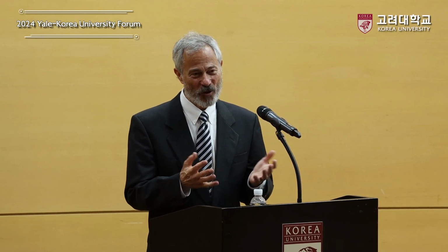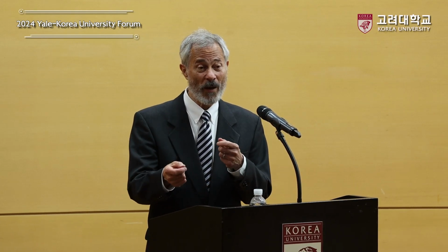So I do think iridium is not necessarily too scarce to be able to do this work. But we're very much interested in trying to find more earth-abundant elements, particularly first-row elements. The real challenge, and this is a challenge facing the entire field, is that the bond energies of ligands to first-row elements are much weaker. And so they rearrange much more readily. And we have not been successful to find a catalyst that's very stable based on a first-row system. And that's going to be a challenge to come up with design principles and design approaches that will give stability. But we're very much interested in other metals, and maybe even a bimetallic system with iridium with another metal might also be a possibility. Thank you.